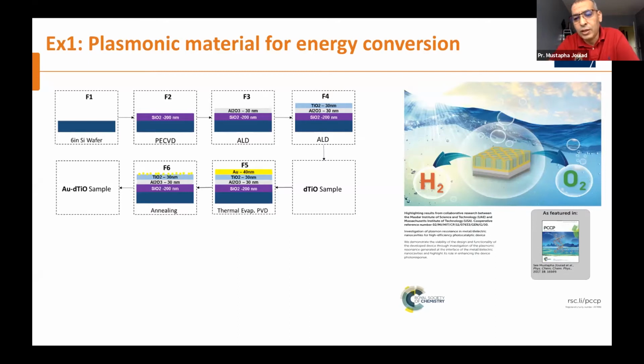For instance, here is gold, for different reasons. The first reason is to increase the absorption of titanium oxide in the full solar spectrum, so at least visible light, which represents 55% of the solar energy. This is one good thing if we add the gold. And another thing, by creating an interface of dielectric and metal, we create what we call plasmonic effects, when the electrons of metals can be excited to reach the conductive band of titanium. And this will help have more electrons in the conductive band of titanium oxide and increase the efficiency of water splitting.